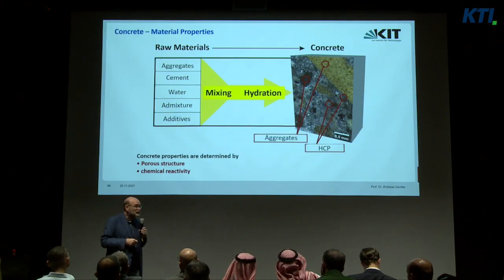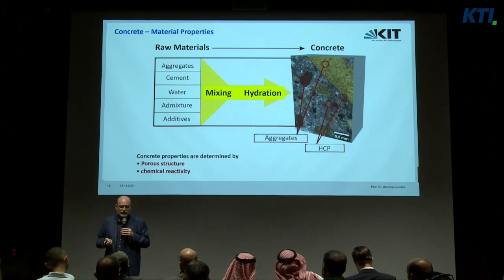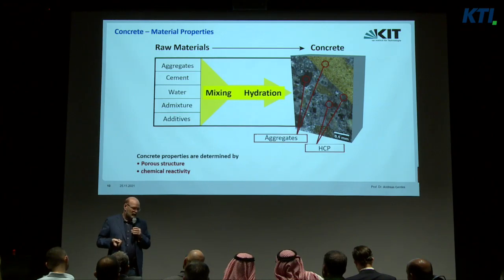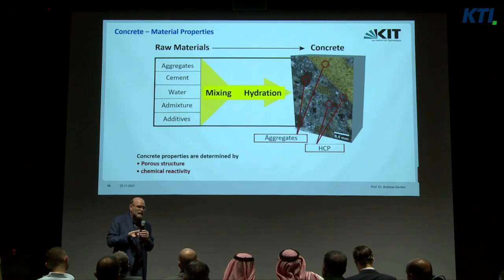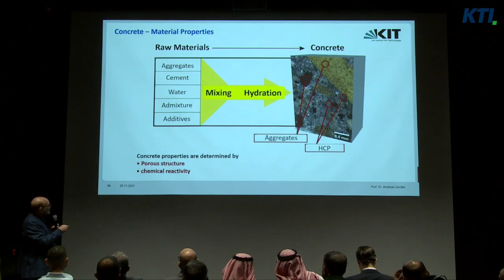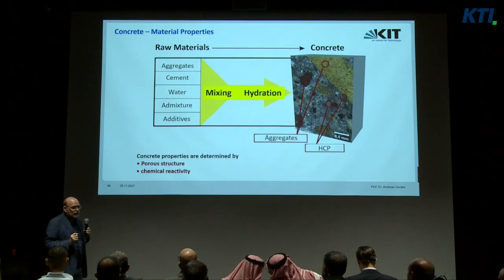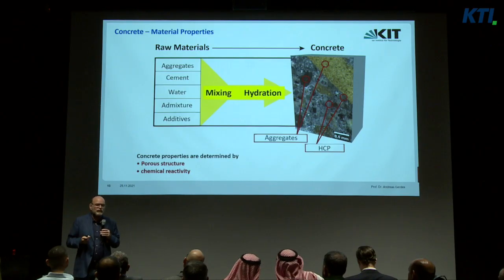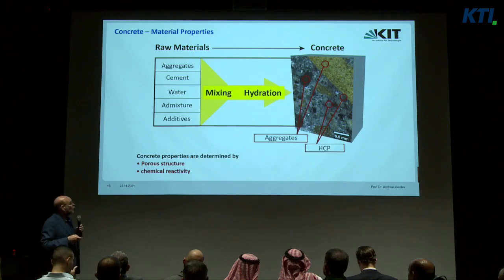So what we have done some years ago, we used cement, put it in a chemical reactor and produced organic compounds in a better way than a classical chemical process. Because this cement works in two ways. First, it collects the water, and second, we have a high pH. And so we get a better result at the end of this technical process compared to classical approaches. So you can use cement for a lot of different things, but you have to take into account that pore structure and the chemical reactivity are decisive for the performance and finally for the durability of the structures.